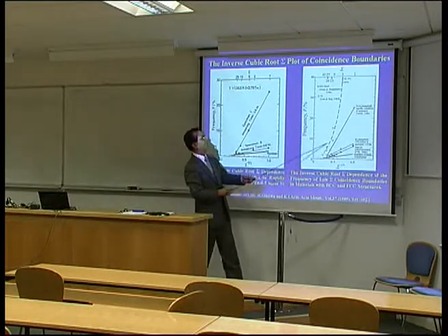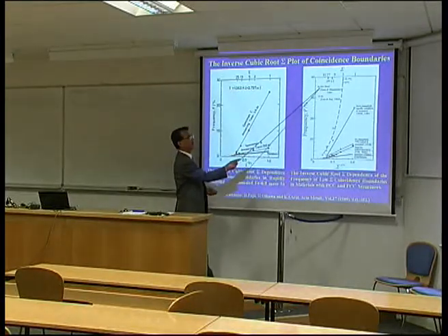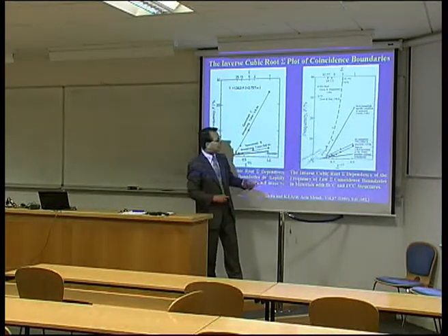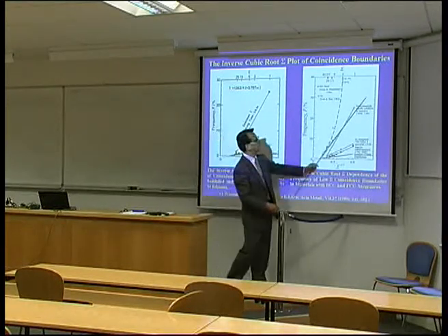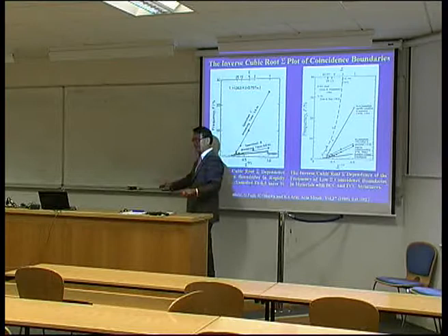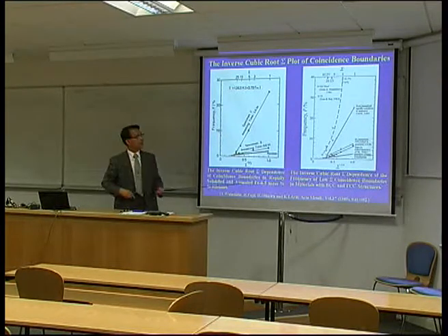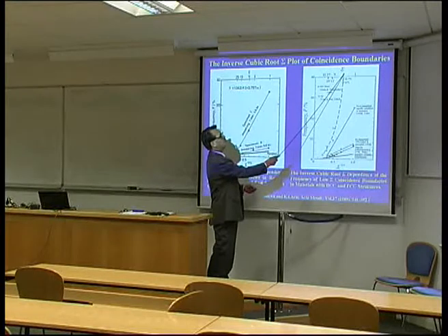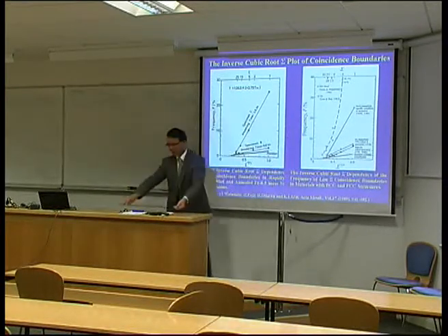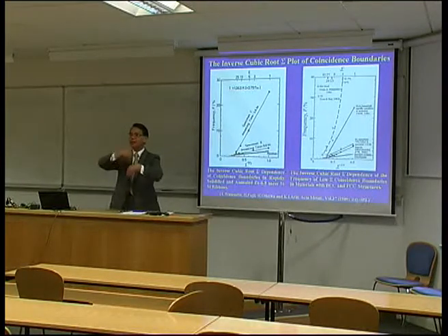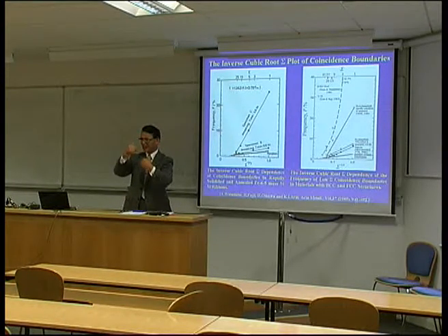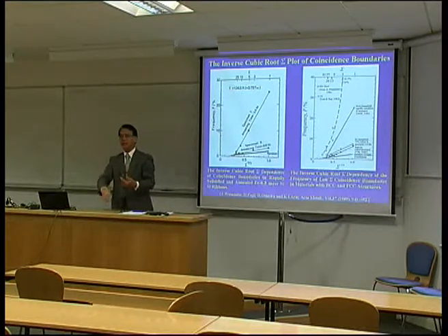But in the case of FCC, like nickel or gamma stainless steel, which has an FCC structure, the frequency deviates from this linear relationship with decreasing sigma value. Because in this case, multiple twinning can occur during annealing. Multiple twinning means sigma 3, 9, 27. Because if one boundary meets another twin, a sigma 9 boundary can occur. And then if sigma 3 and 9 meet, we can produce another, sigma 27.